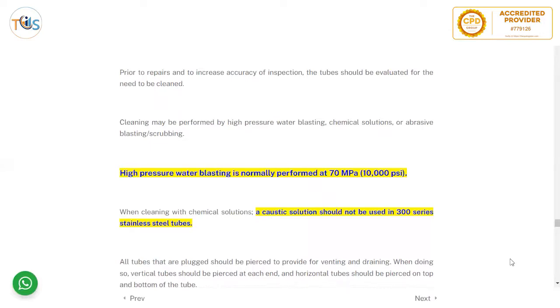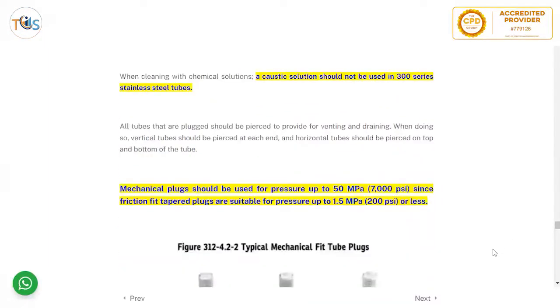And cleaning can be performed by high pressure water blasting, chemical solution, or abrasive blasting. High pressure water blasting is normally 70 MPa or 10,000 psi. When cleaning with chemical solution, caustic solution should not be used on 300 series because of chloride content in them, and it can damage the 300 series stainless steel tubes. And all tubes that are plugged should be pierced to provide for venting and draining. When doing so, vertical tubes should be pierced at each end, and horizontal should be pierced on top and bottom of the tube.